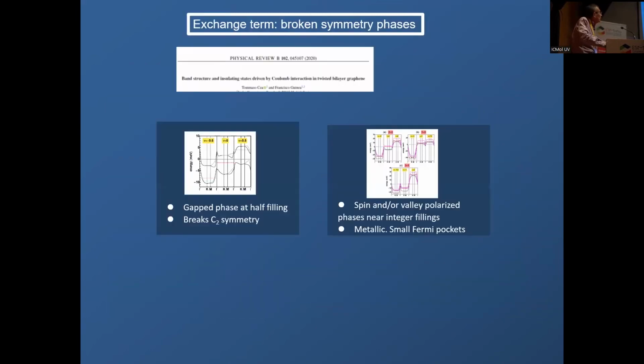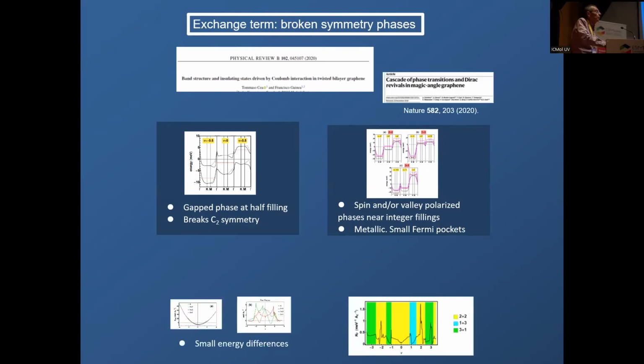And these are other calculations. As I said, this calculation is a Hartree-like calculation in terms of an effective potential, which you build up when you dope the system, and it explains the width of the band observed experimentally. And to describe other insulating phases, you have to go from Hartree to Hartree-Fock. It's more complicated, but it's doable. Hartree-Fock doesn't give you superconductivity, it gives you spin or valley polarized phases, or phases with a gap. And there are very many phases nearby with very small differences in energy from phase to phase.